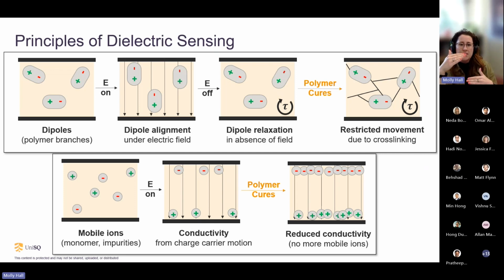So with your electrodes, in this sensor, you're essentially fluctuating an electric field on and off constantly, and there are multiple frequencies that you can set that to. So when your electric field goes on, your dipoles align under the electric field. Your ions also start to move from one electrode to another. But then the electric field goes off and your dipoles relax and your ions stop moving. And essentially you keep doing this constantly through cure.